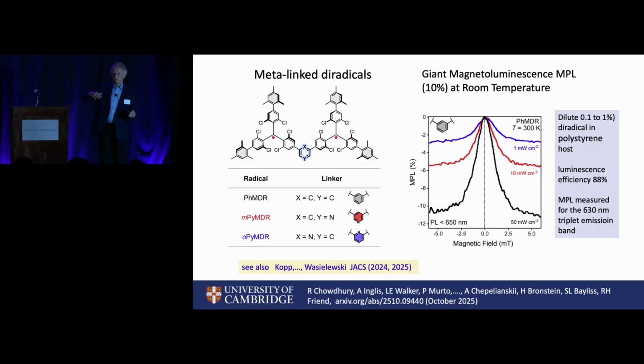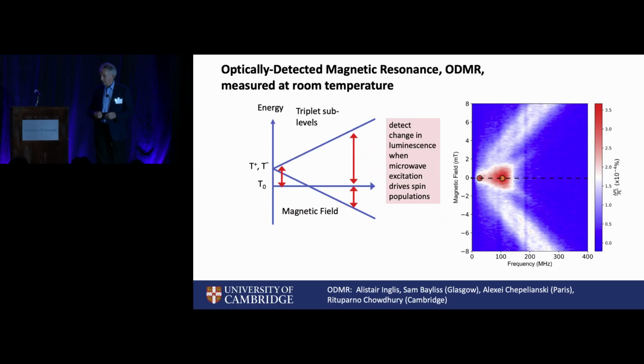So if you want to be able to tell whether you've got something embedded in something biological, and you can see it blink, see its luminescence modulated by simply bringing a magnet near it, that's not very high technology, and it looks quite useful. In detail, it's all to do with changes in the ground state between the 3 sublevels of the triplet, and that you can pick up with optically detected magnetic resonance.